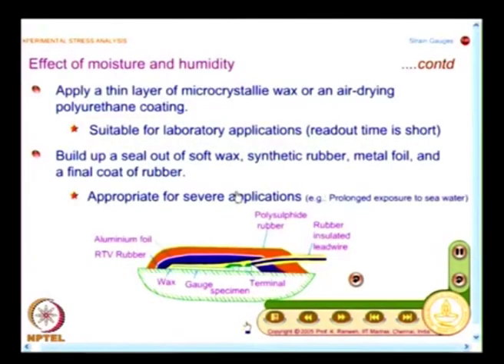I said water is elixir of life, but water is very bad for strain gauge installation. We saw strain gauge installation need to be protected against moisture. So, when you learn that it has to be protected against moisture, one of the simpler approaches is apply a thin layer of microcrystalline wax or an air drying polyurethane coating, and this is good enough for laboratory measurements, and your readout time is essentially short.